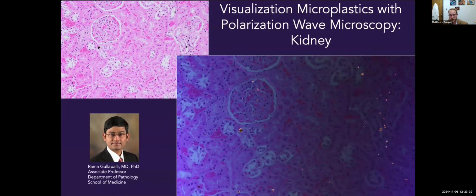It doesn't tell us much about the anatomy, unfortunately, unless we can do these sort of big, large-scale digestions. So I've talked with a number of our pathologists to get a better handle on where these might be. Rama Gulapalli is an associate professor in our Department of Pathology, and he's employing a modified approach to a polarization wave microscopy technique. This is cool. It looks at these inclusions and identifies those inclusions that have a refractile property.